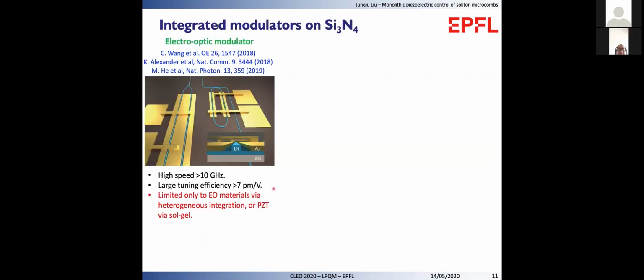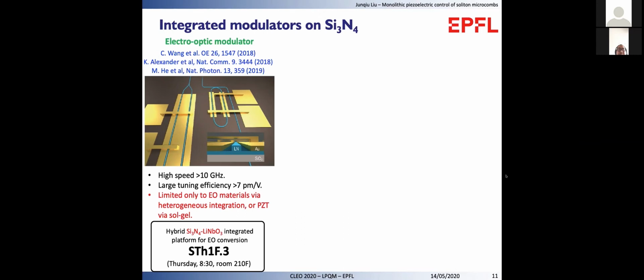As silicon nitride is an insulator, the implementation of optical modulation on silicon nitride is challenging and typically requires other materials to assist. Electro-optical modulation can be realized by heterogeneous integration of EO materials on silicon nitride. The integrated EOM features high speed above 10 GHz and large tuning efficiency of 7 picometers per volt. However, the disadvantage of this scheme is that it is only limited to EO materials by heterogeneous integration, or PZT via sol-gel. During CLEO, my colleague will also present our recent progress on a hybrid silicon nitride lithium niobate integrated platform for EO conversion.